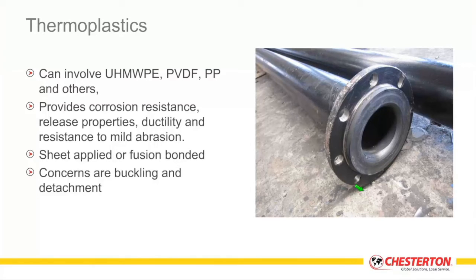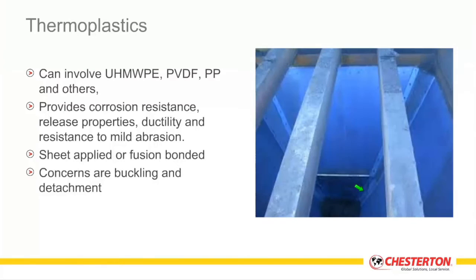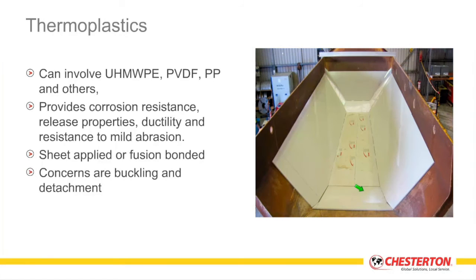So examples here is a thermoplastic liner to the internal of a slurry pipe or chemical slurry pipe. Here you see materials used in a hopper where you're looking for better release properties. So you don't want hang up on the walls, so your ultra-high molecular weight plastics give you good release characteristics, allowing the material to flow in a mass flow approach down into your process. You also see haulage buckets in off-road trucks being used to get better release of the materials, so you're not getting hang-ups, so the yield of the bucket is much higher. You get better fuel efficiency and better transport efficiency as you move your ores around the plant.